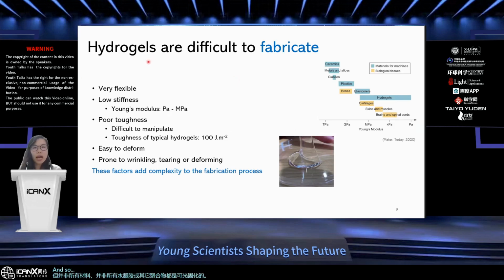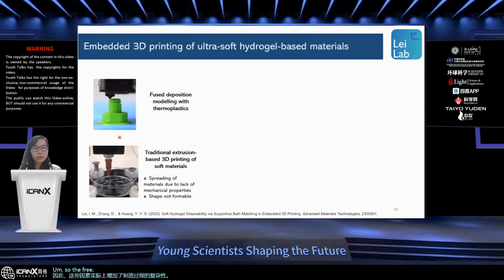Hydrogels are particularly difficult to fabricate into 3D shapes because these materials are very soft, and they have low stiffness, poor toughness, and they are very easy to deform. So these factors add a lot of complexity to the fabrication process. The videos here show that if we utilize traditional extrusion 3D printing to print the soft materials, most of the time the materials will spread due to the lack of mechanical properties. So basically, it is very difficult to form the shape of the hydrogels using traditional extrusion-based 3D printing.